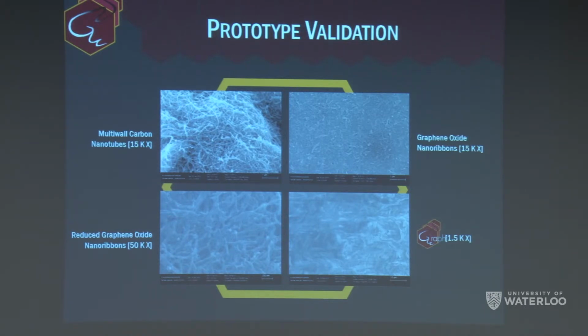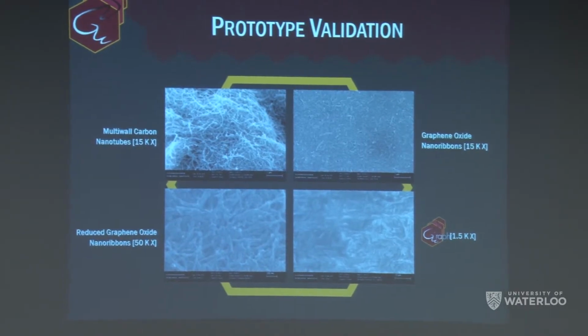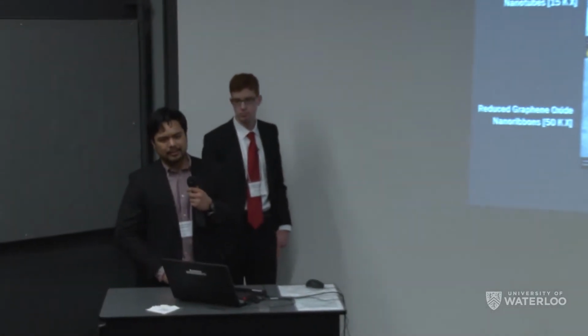And to the right of that, you can see our graphene oxide nanoribbons. This is following the KMnO4 H2SO4 unzipping process. As you can see, there's a change in morphology. It's no longer a tubular structure, but it looks more flattened. If you were to measure the width of the structures, you'd see that they're roughly equivalent to 100 nanometers, which is what you would expect when you unravel our purchased MWCNTs. We then reduce these graphene oxide nanoribbons to get the reduced graphene oxide nanoribbons.